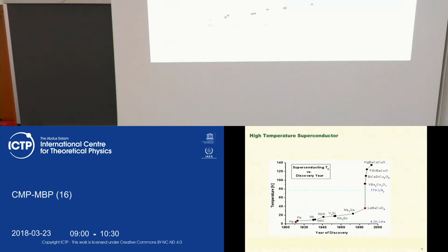Okay, this is how the history developed. This is mercury, 1911, then lead, niobium, niobium nitride, niobium carbide, niobium-3 tin, niobium-3 germanium. And it took, as I said, 70-something years for the temperature to increase from 4 Kelvin up to 24 Kelvin. And then there was a breakthrough with lanthanum, barium, copper oxide. This is the system for which Bednorz and Müller got a Nobel Prize, and then there was an almost vertical step with a new compound. However, there was a breakthrough around 1986, 1990, and then again the system saturates.